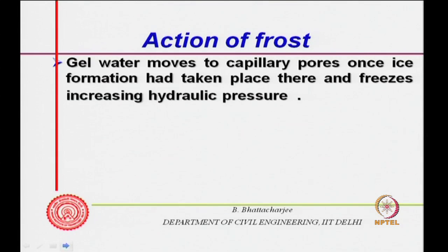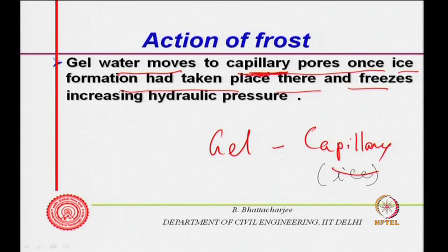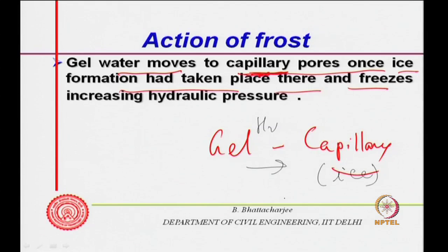There is an additional mechanism. When capillary pores become ice, the vapor pressure reduces. So, once ice formation has occurred in the capillary pores, the vapor pressure would reduce. So, gel water will move to the capillary, because ice has formed here. Therefore, water will move from gel to capillary, and then again it will get frozen and the hydraulic pressure will increase.